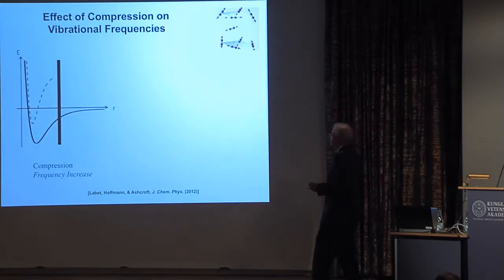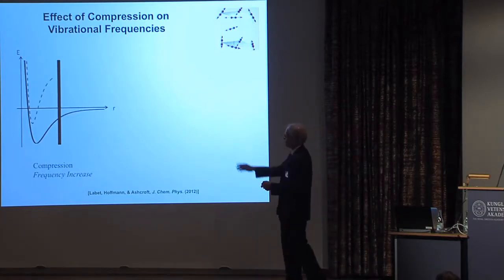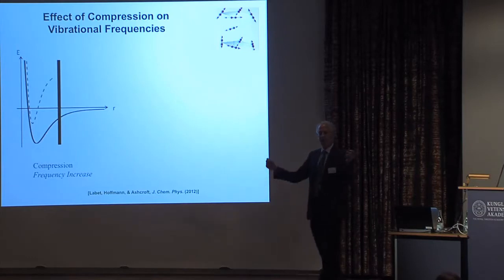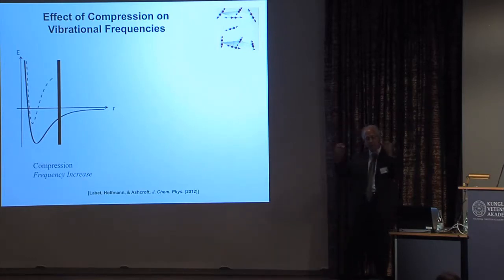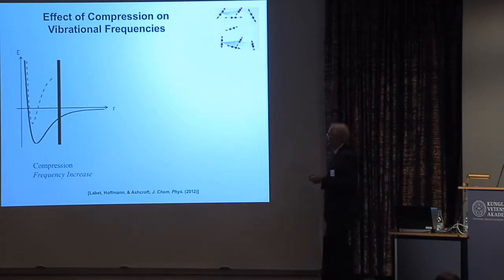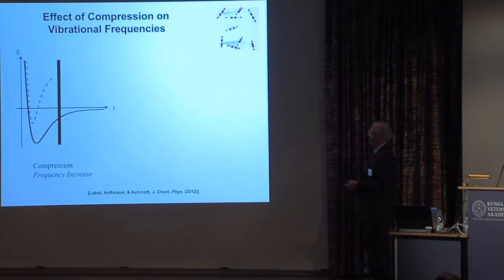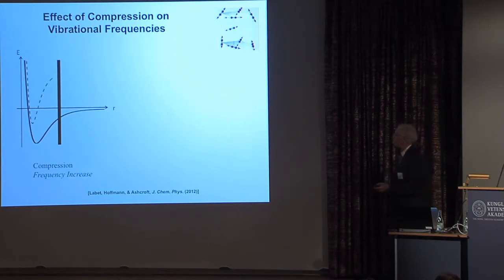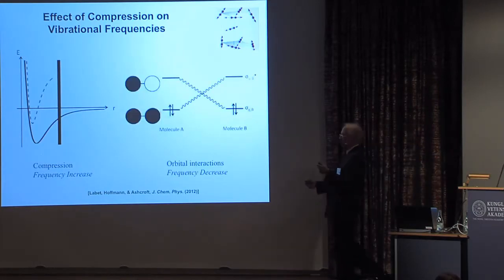Well, there are really two effects. So here's an intramolecular potential, and with increasing pressure, as you pack more molecules around a given molecule, you stiffen up that potential, and this causes an increase in frequency with increasing pressure or increasing density. Well, there's a competing effect, and that is due to orbital interactions.